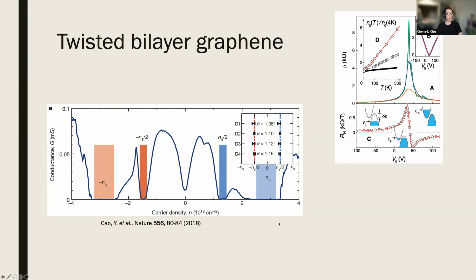So at MIT, they figured out how to make a magic angle twisted bilayer graphene. When you twist your graphene to a magic angle and you create a perfect Moiré pattern, you will get your flat band very, very flat, so that the interaction can be so strong that it creates some extra behavior. If you remember, in the monolayer graphene, you only have a Dirac cone feature. When you gate the sample to the Dirac cone, you have a high density of states, but that's it. You don't get anything outside of that.